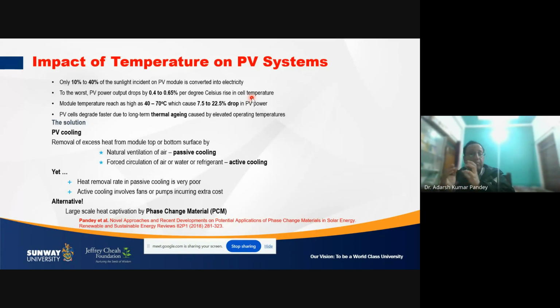So you need a proper mechanism where you can manage the temperature close to 25 degrees centigrade so that you get the maximum power output. You can do this utilizing different methods. One is natural ventilation of the air, which is known as passive cooling, or forced air or water or refrigerant, which is known as active cooling. But when you are using water or refrigerant, the problem is that this is active cooling. You need a pump to pump the water or refrigerant. So as an alternative, you can go for the phase change materials. You can directly apply the phase change material to the panel.